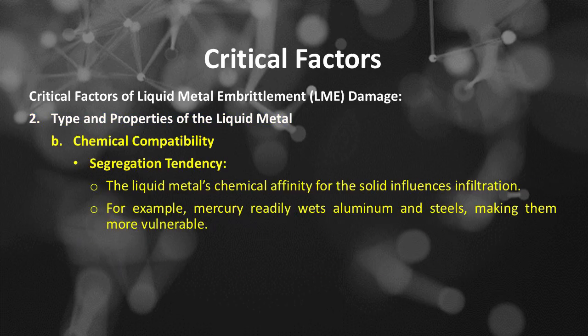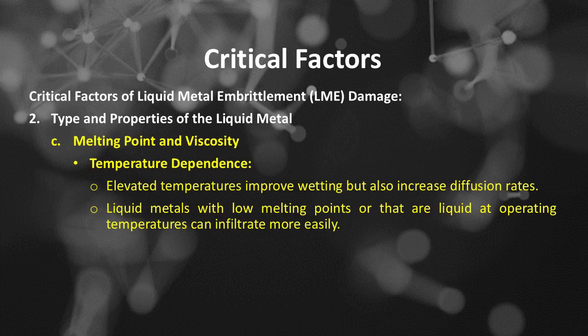Type and properties of the liquid metal. Number B is chemical compatibility, segregation tendency. The liquid metal's chemical affinity for the solid influences infiltration. For example, mercury readily wets aluminum and steels, making them more vulnerable. Number C is melting point and viscosity, temperature dependence. Elevated temperatures improve wetting but also increase diffusion rates. Liquid metals with low melting points or that are liquid at operating temperatures can infiltrate more easily.